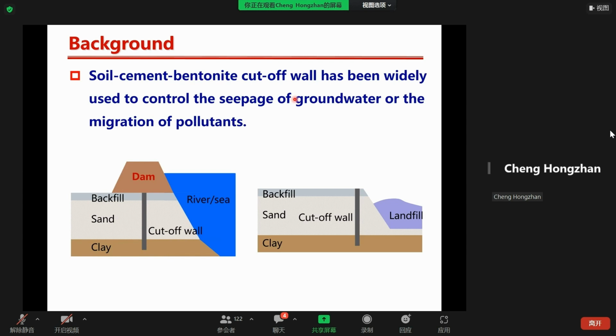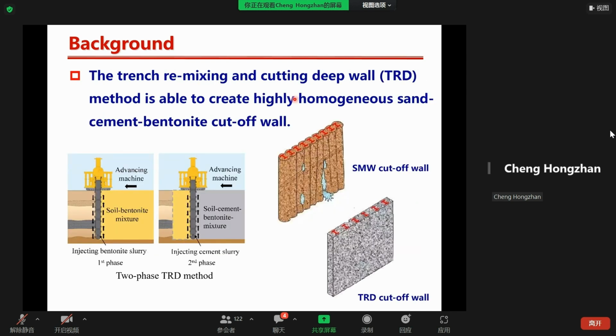But recently, soil cement bentonite cut-off walls have been used more frequently because they have high strength with the addition of cement slurries. The trench cutting re-mixing deep wall (TRD) method is able to create highly homogeneous soil cement bentonite cut-off walls compared to other in-situ mixing methods like deep mixing. In general, the TRD cut-off wall can be constructed using the one-phase method or the two-phase method, as shown in this picture.